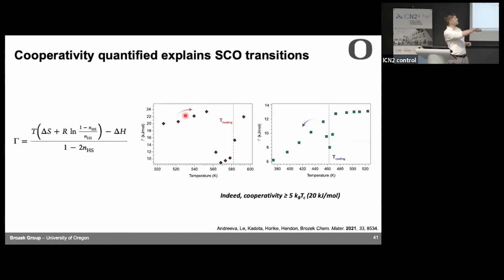We plot that as a function of temperature. It goes to infinity at the spin crossover temperature, but you can look at what the cooperativity is away from the spin crossover temperature. It's around 20 kilojoules per mole. Turns out that's exactly 5 times kT. So just as people predicted in the 70s, you get this really sharp box-like spin crossover behavior when you have a huge amount of cooperativity. That was completely consistent with what they predicted.